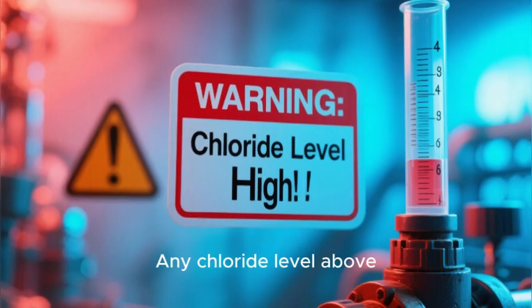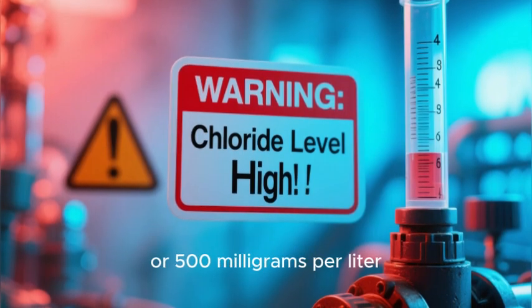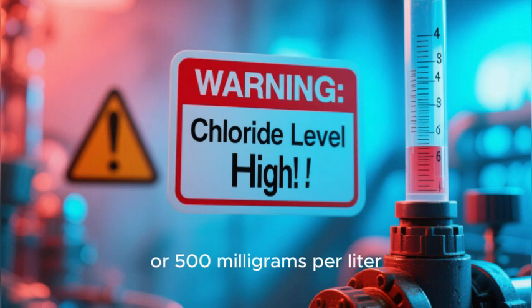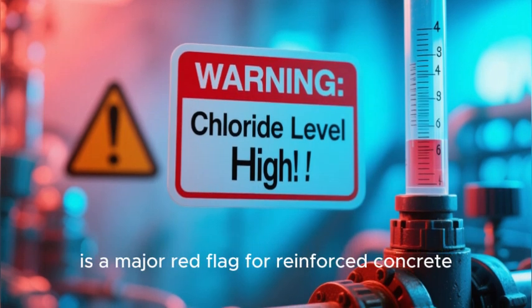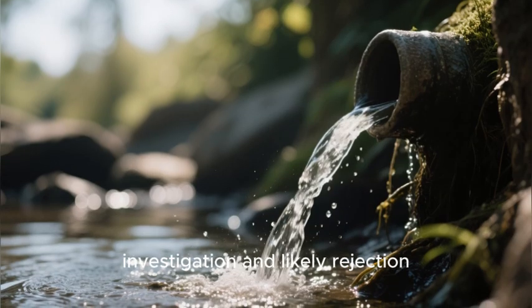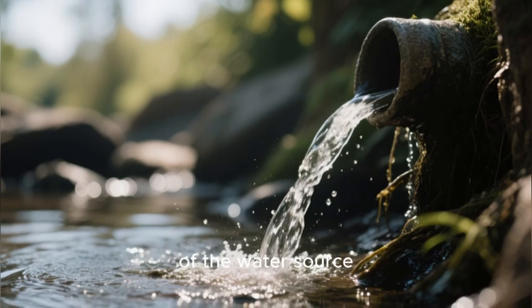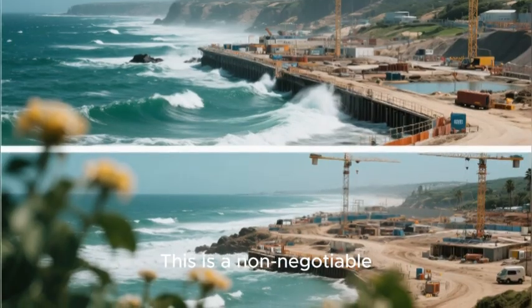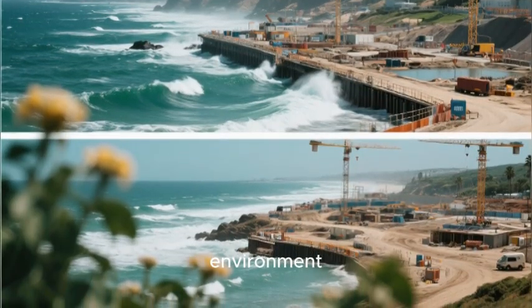Any chloride level above 500 parts per million, or 500 milligrams per liter, is a major red flag for reinforced concrete, and requires immediate investigation and likely rejection of the water source. This is a non-negotiable check for any structure in a coastal environment.